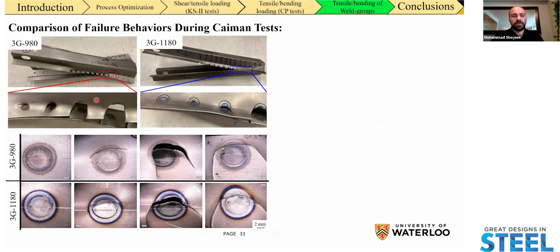I've shown representative micrographs here. These are the last four welds that are failing by the end of the Caiman test at 250 millimeters of displacement. You can see that we're continuously getting a complete pullout failure from the 3G 980 material, characterized by failure starting from outside of the nugget and then propagating around the periphery of the nugget, giving us a relatively high plug ratio. Whereas in the case of the 3G 1180, we're typically getting partial interfacial, partial pullout, where we have crack propagation inside the fusion zone, giving us a relatively smaller plug ratio by the end of the test.